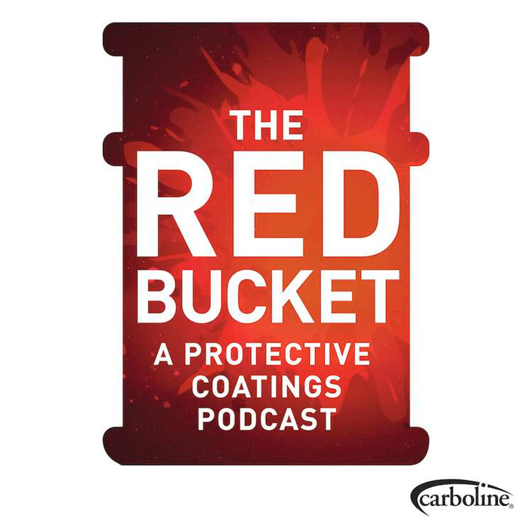So if there's damage, if there's big rain cycles, heavy rain cycles, or wind, sand abrasion, eventually those outer layers of zinc will erode away. And of course, depending on where you are, that process can be more rapid, and in a lot of areas, it's going to be fairly slow. It's somewhat similar to what you see with weathering steel. Of course, it's very different.